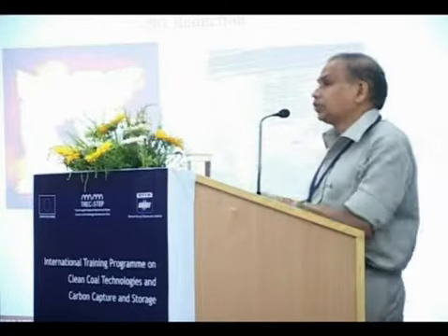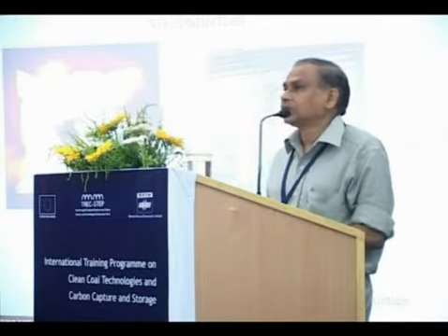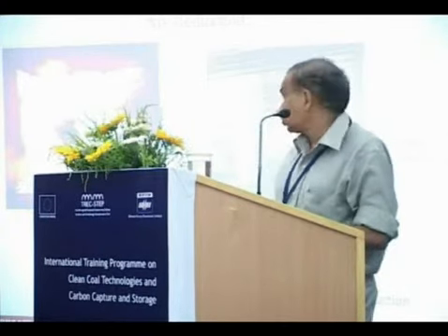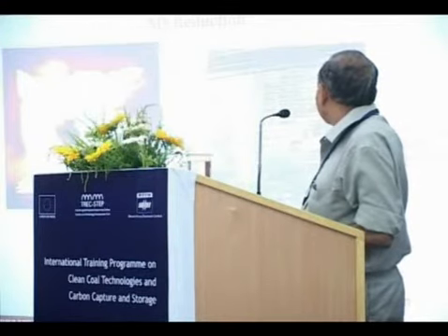Now to reduce the NOx levels, apart from the tangential fired boilers, which are inherently low in NOx, producing about 260 grams per gigajoule, that is about 430 ppm or 750 milligram per normal cubic metre, we also have a bypass overfire air system, so that the amount of air introduced in the furnace is retarded and then put above the furnace, so that the thermal NOx produced is less in the combustion cycle. This has been put as a retrofit in one of the power stations, and this has yielded a result of about 30 to 40% reduction from the current NOx levels. So here we have the tangential firing, which is inherently producing low NOx, in the order of 750 milligram per normal cubic metre or 430 ppm. Over and above that, we can reduce about 30 to 40% by going for bypass overfire air. This is one of the retrofits that has been done in one of the 250 megawatt boilers.